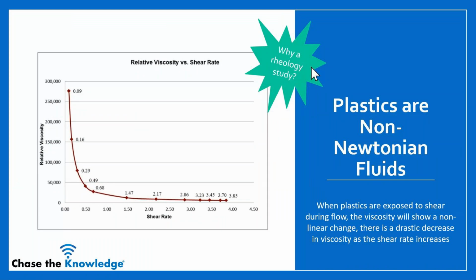I've been mentioning taking advantage of the shear thinning behavior. So what is this? When plastics are exposed to shear, like I said, we get an untangling. At solid, you have just an entangled mass of polymer chains. As we heat them, those chains start to increase their intermolecular spacing. You can think about this like the chains getting a little further apart. Once they're hot enough to be far enough apart that we can slip them past one another, we have flow. As we flow them at higher rates, we get orientation and alignment. That orientation and alignment is what drives our viscosity down. That's what makes a polymer a shear thinning material.